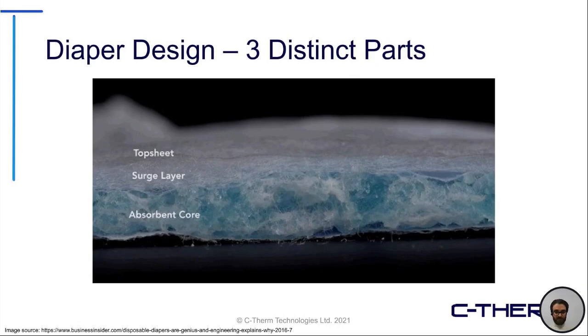If you look at the overall diagram or the design of a diaper, they have three main components. There's the top sheet, which is the material that's in direct contact with the skin. Then there's the internal surge layer, which is the material that's pulling that liquid or moisture away from the top sheet and bringing it in through the body of the product itself. And then the absorbent core is where that moisture is retained, so it doesn't leak back up into the top sheet and obviously introduce more of that cooled sensation. So by modifying the different materials that are used in the overall structure, this will influence the overall thermal properties of that material type itself.